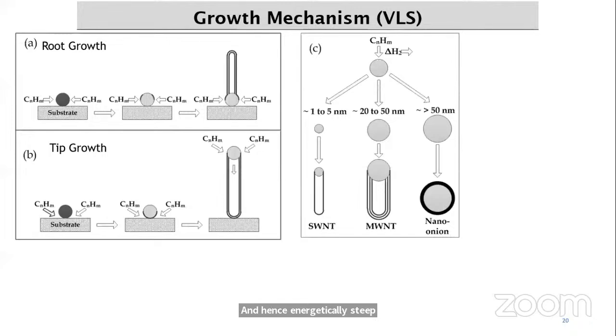Now, the hydrocarbon decomposition releases some heat to the metal exposed zone. While carbon crystallization takes place, since it is an endothermic process, it absorbs some heat from the metal's precipitation zone. This precise thermal gradient inside the metal particle keeps the process going.